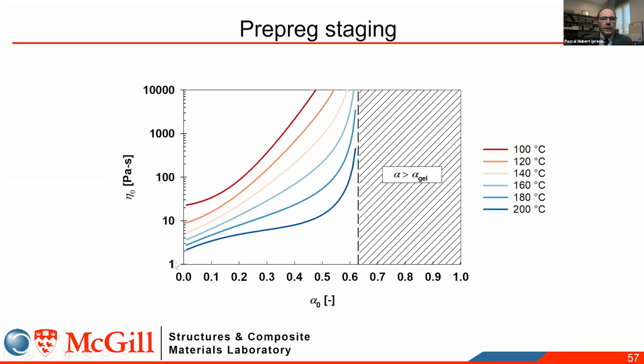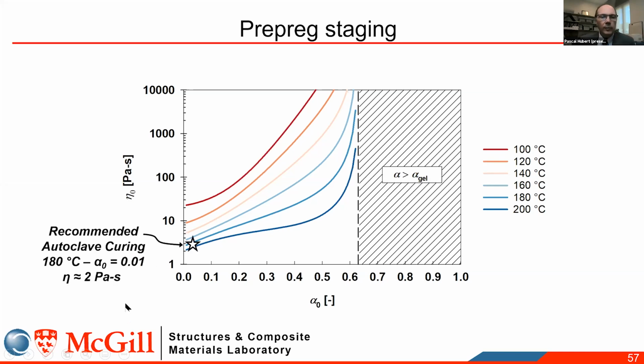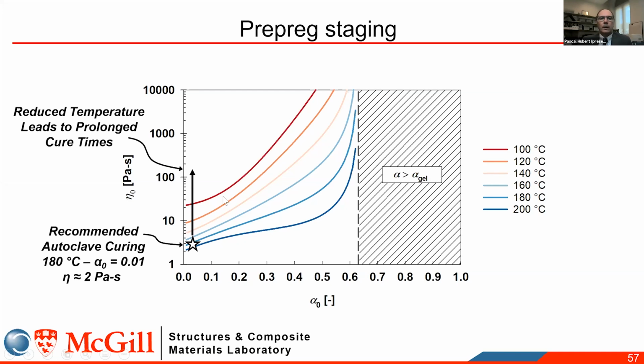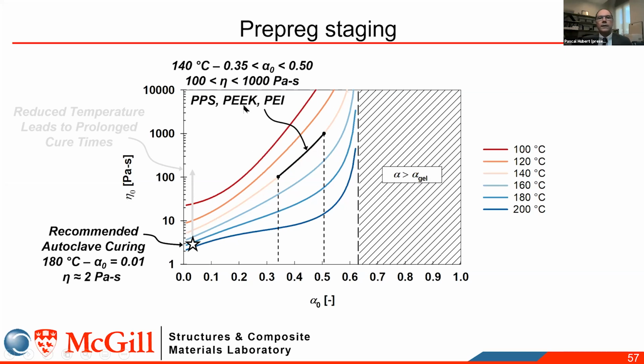This is done through pre-preg staging. Here I'm showing you a viscosity map versus initial degree of cure, and the different lines represent different curing temperature protocols, from low temperature to high temperature. If you take an autoclave pre-preg, it's usually cured at 180 degrees Celsius, and it starts fresh, so very low viscosity and very low degree of cure. If you want to increase the viscosity of the resin during cure, you will have to cure it at a lower temperature. And that will take forever because the cure kinetics of that material is not optimized for low temperature cure. In order to have your shear flow behavior, you want to be in that range of viscosity. This is typical of the thermoplastic composites that flow predominantly by shear.